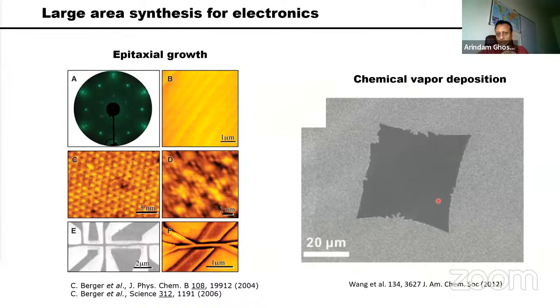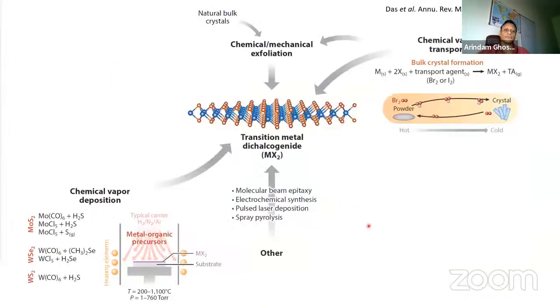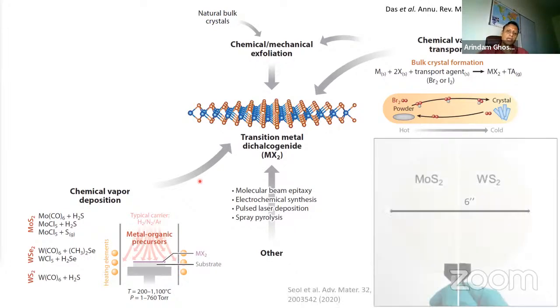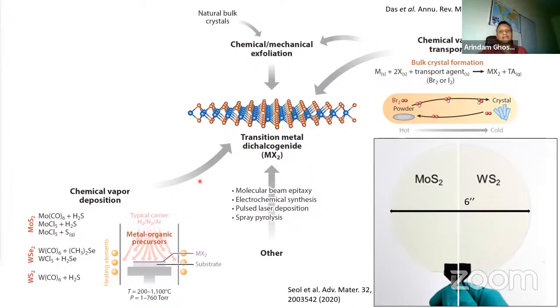Or chemical vapor deposition is also an extremely important and probably a more promising way of getting two-dimensional materials on a variety of substrates. Not just graphene, which you see here, but also the transition metal dichalcogenides, which are grown using several bottom-up techniques, molecular beam epitaxy, then pulse laser deposition, spray pyrolysis. But chemical vapor deposition is one of the most important areas of growing these on sapphire, silicon oxide, and several substrates. We now have 6-inch wafer scale growth of high quality molybdenum disulfide, tungsten diselenide, tungsten disulfide layers, single layer over the entire wafer, that can now go to technology.